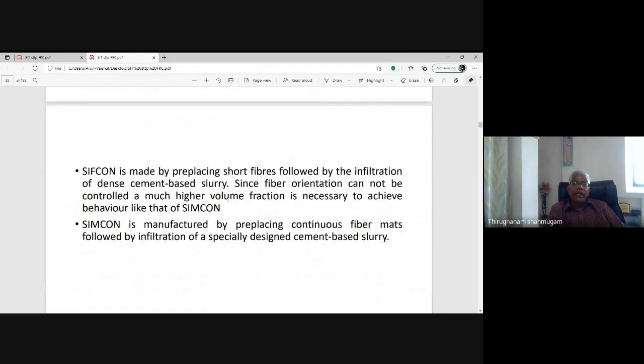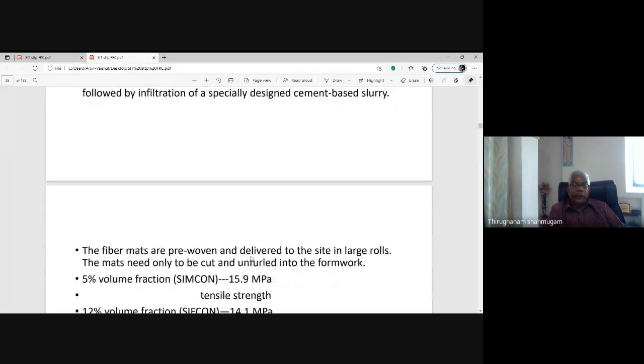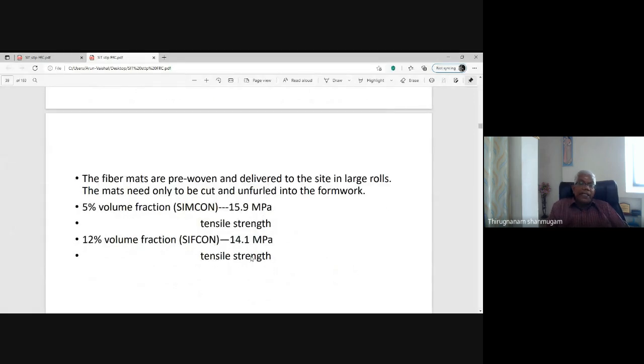SIFCON is made by pre-placing steel fibers followed by the infiltration of a dense cement-based slurry. Since fiber orientation cannot be controlled, a much higher volume fraction is necessary to achieve behavior like that of SIMCON. SIMCON is manufactured by pre-placing continuous fiber mats followed by infiltration of a cement-based slurry. It is a comparison. The fiber mats are pre-woven and delivered to the site in large rolls. The mats need only to be cut and unfurled into the formwork.